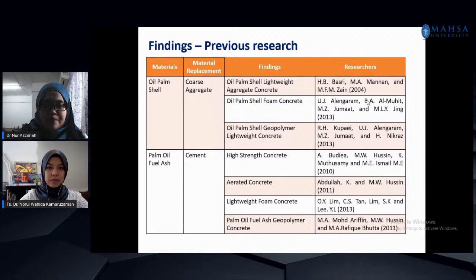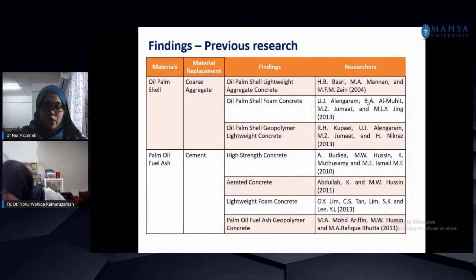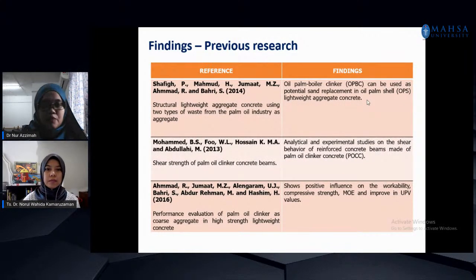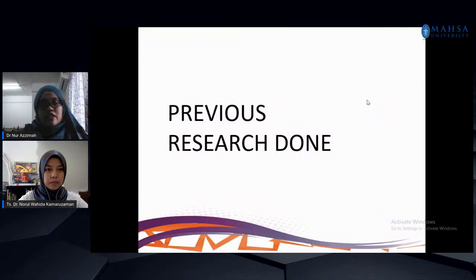Same goes to the palm oil fuel ash. It has been used in the partial replacement of cement inside the high strength concrete, and then in aerated concrete, foam concrete, as well as geopolymer concrete, right? And the palm oil clinker also has been used before. They use it as a coarse aggregate replacement, and also sand aggregate replacement to produce beams, high strength lightweight concrete. For the palm oil clinker, usually it can produce a very high strength concrete, which has good potential to be used in the construction of the bridges and high rise buildings. So we can use this high strength concrete. So these are the previous research that we have done.